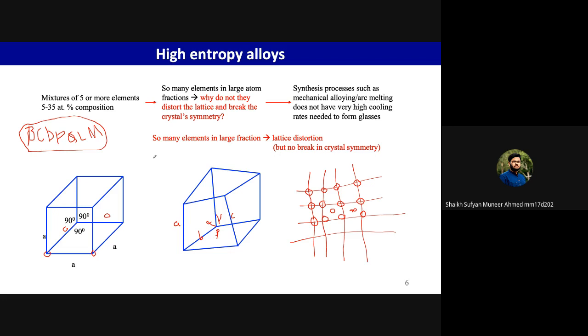Because you need to have very high cooling rates, more than a million degree Kelvin per second, to prevent these atoms going into the nearest lattice site. And the diffusion distances are very small, angstroms to picometers. And the surprising thing is, most of the people who are working in high entropy alloys have come from metallic glass research, bulk metallic glass research. Professor B.S. Murthy was also a metallic glass person before he shifted to high entropy alloy. You just change the cooling rate: you have a glass, you make the cooling rate slow, you have a high entropy alloy.